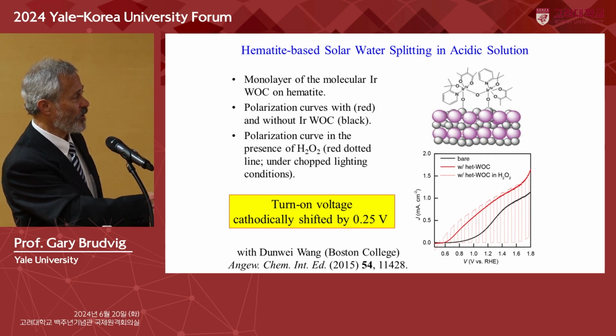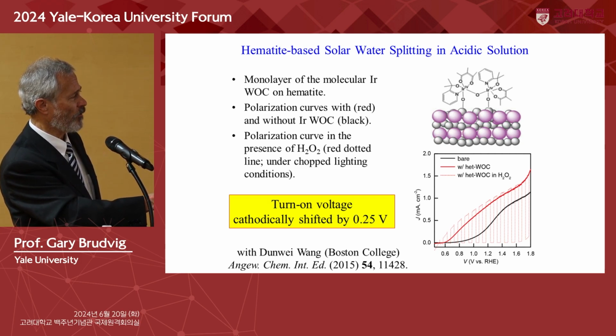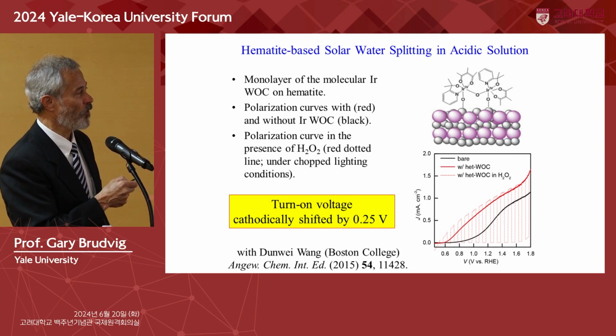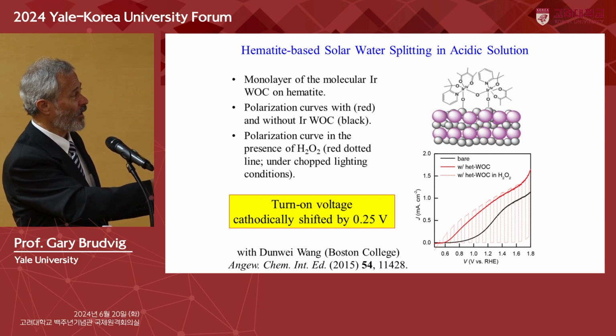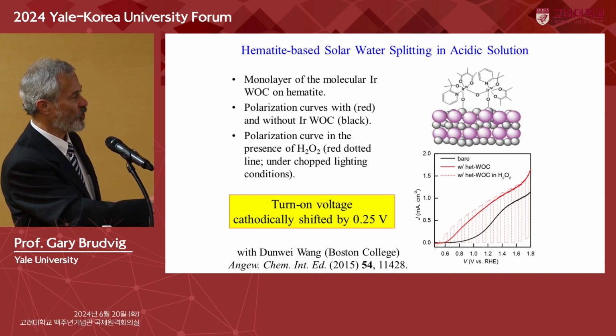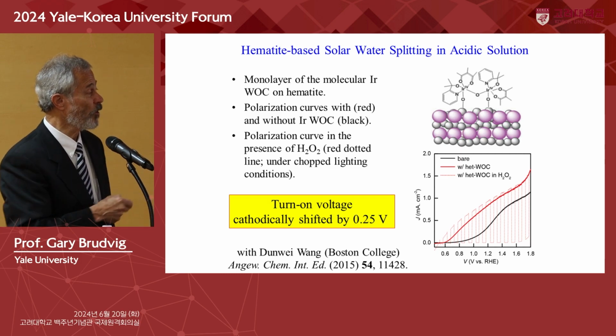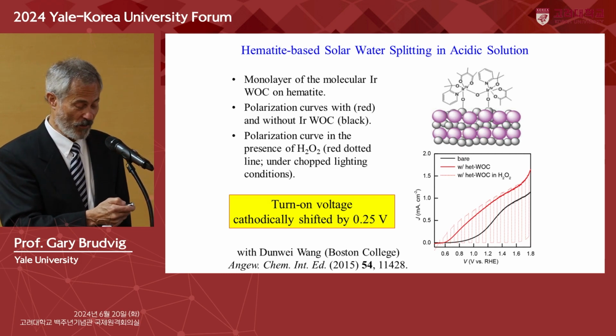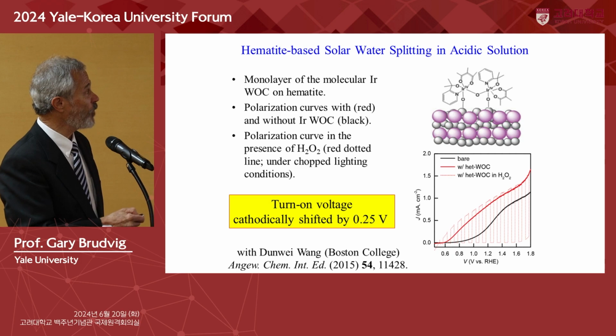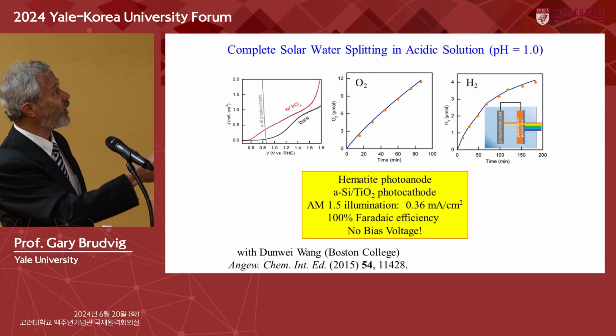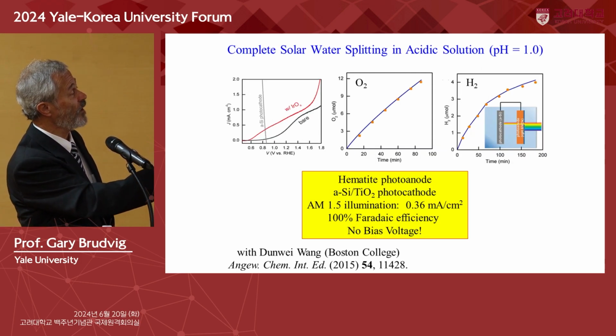And you can see there's a turn on somewhere around a volt for photocurrent. If we put our catalyst on the surface, this iridium blue catalyst, we can see it shifts by several hundred millivolts to lower voltage. So we're significantly improving the photocatalytic performance. And we've been able to use this to make complete solar water splitting cells.